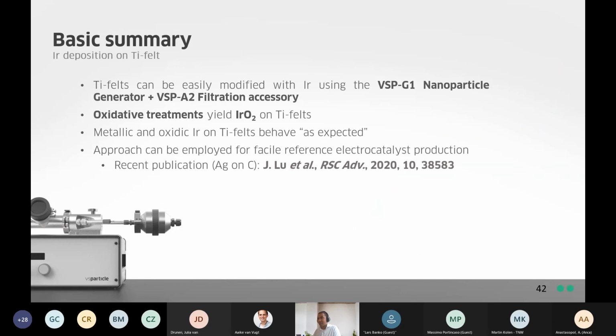So just a basic summary of this stage. The titanium felts can easily be modified with iridium using the VSP-G1 nanoparticle generator equipped with the VSP-A2 filtration accessory. After an oxidative treatment, we obtain iridium oxide nanoparticles on these titanium felts. And while the metallic and oxidic iridium on the titanium felts behaved as expected, we use this more as a way to show that we can readily and easily prepare reference materials for electrocatalytic studies.